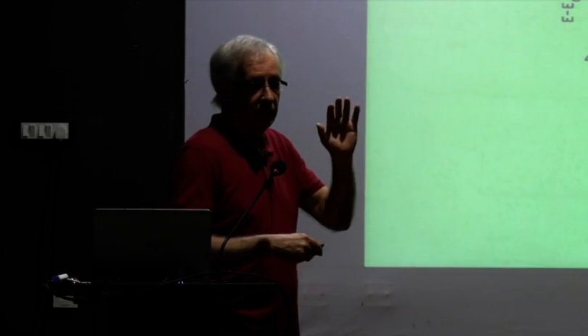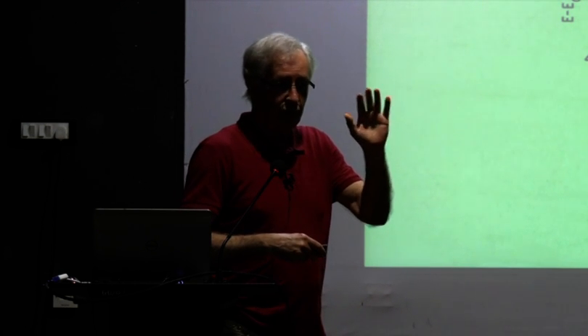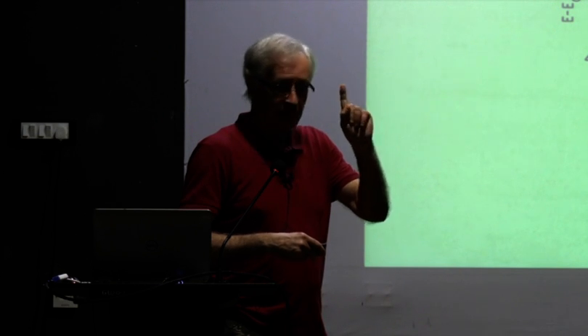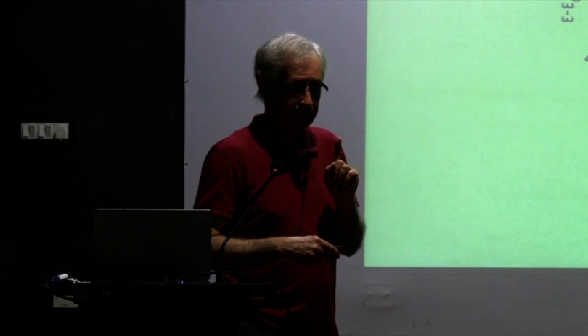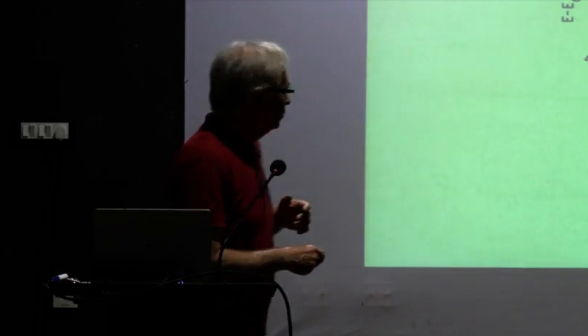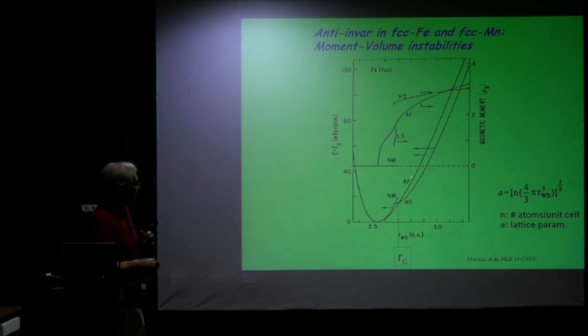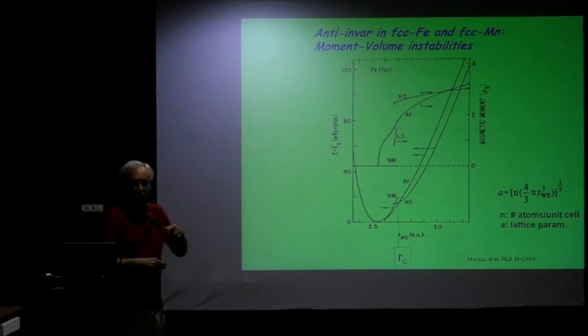You look at certain states which you want to give in as input. One is the ferromagnetic state, and the other is the antiferromagnetic state, and perhaps a non-magnetic state. When you do that, what you find is that for the antiferromagnetic state, the binding energy follows a curve something like this. And the antiferromagnetic moment looks something like this. This here is the equilibrium volume. So under equilibrium conditions, the magnetic moment of the antiferromagnetic state or the non-magnetic state should be nearly zero.